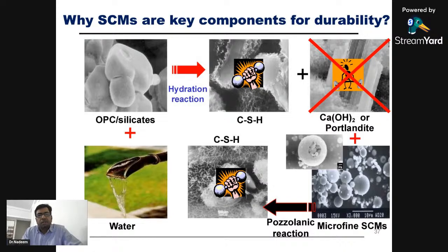With the water, the formation of CSH happens, and byproduct is in the form of calcium hydroxide, portlandite, which we don't want, which is unstable. It reacts again, maybe with carbon dioxide, and leaches out by forming calcium carbonate. So we don't want this product, which is unstable. Again, we want it to react with pozzolanic material. Again, it reacts and forms the CSH. These are the cycle of components for the durability.